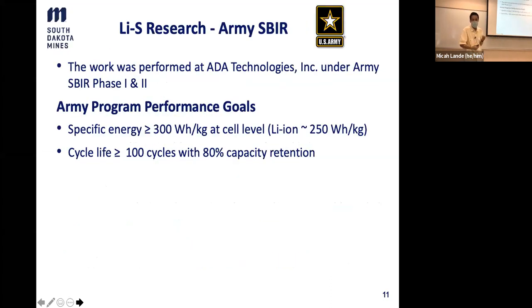So when I was at ADA Technologies, we carried out lithium-sulfur research under the Army SBIR phase 1 and phase 2. The Army's program goal was for the specific energy of the cell, and we're not talking about the material. Previously I showed the large number, that's for the material. Here, with everything put together, the whole cell needs to be more than 300 watt-hour per kilogram. Compared to lithium-ion, which is about 250, it's about 20% more. And then the Army also asked for a cycle life of more than 100 cycles.